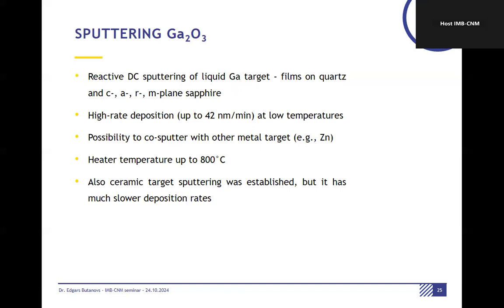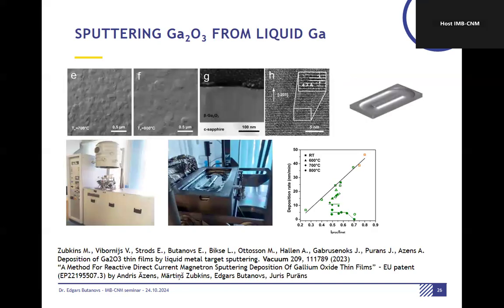And in terms of our capabilities, which is not very common for sputtering systems, we can have substrate temperatures up to 800 degrees, which is nice for obtaining highly crystalline films. And typically our developed DC process has much higher deposition rates than ceramic target sputtering, this RF, which is commonly employed for gallium oxide.